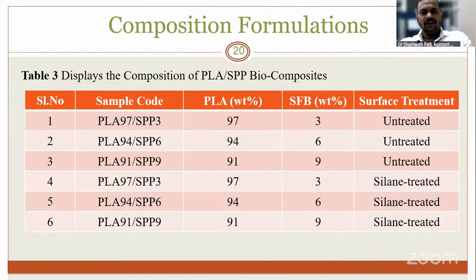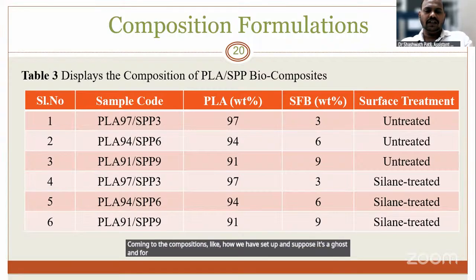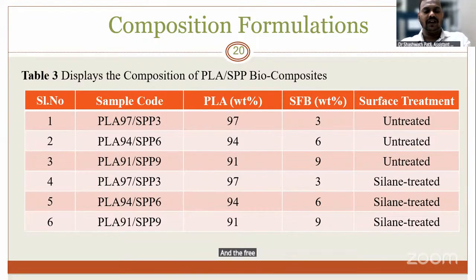Okay. Coming to the compositions, how we have split up the composition for our study. We have done two sets, as I said earlier. In each set, we have done three compositions of 97% of the matrix material PLA and 3% of the filler, split pen powder, and then 6% and 9%. Similarly, we have varied 3, 6, 9 for the silane treatment.